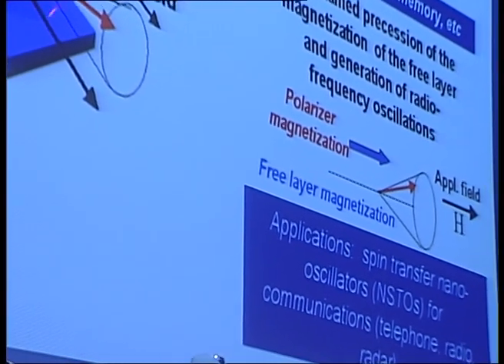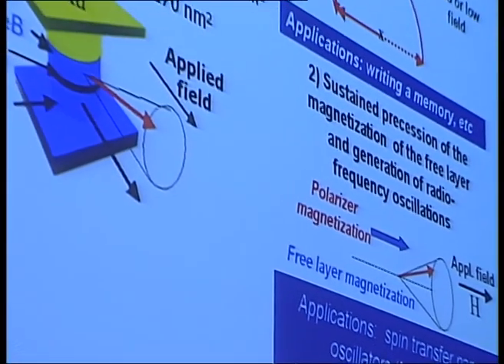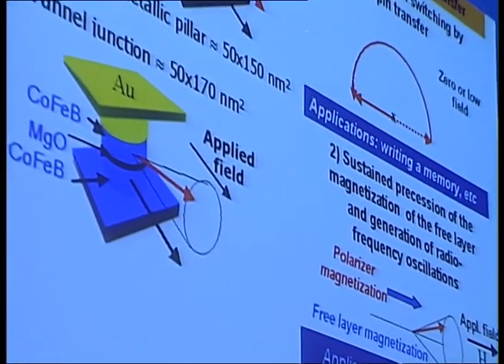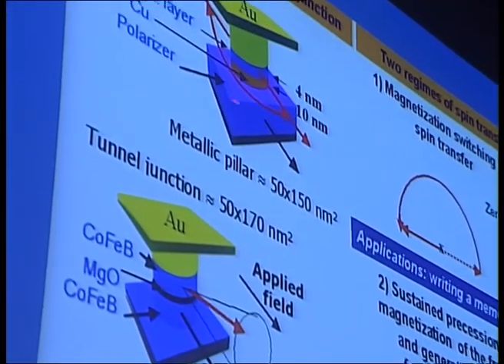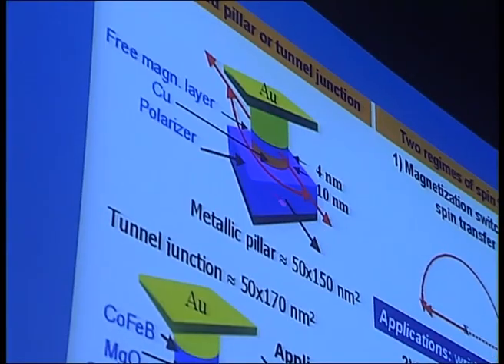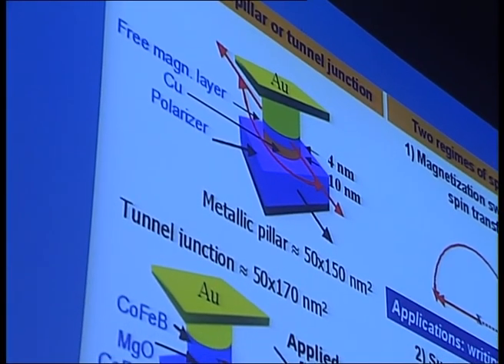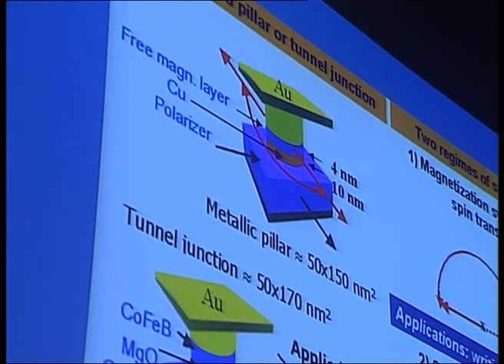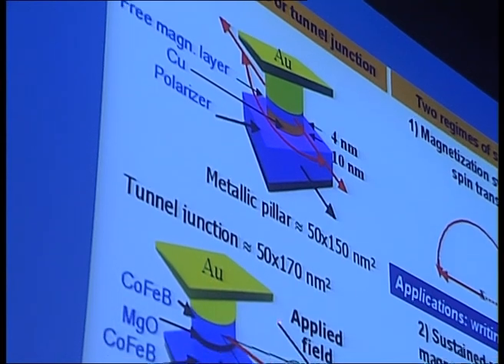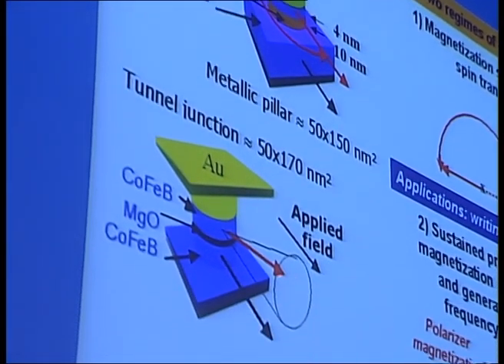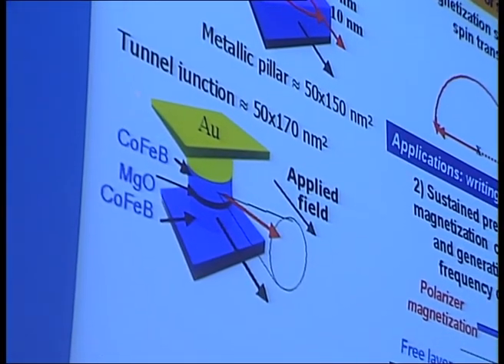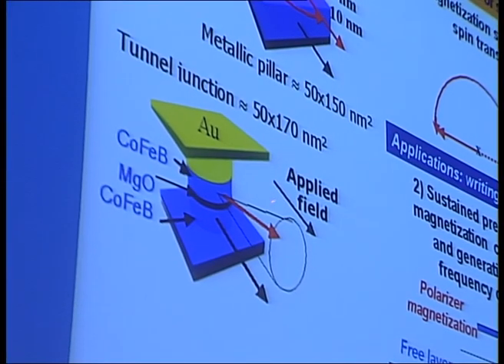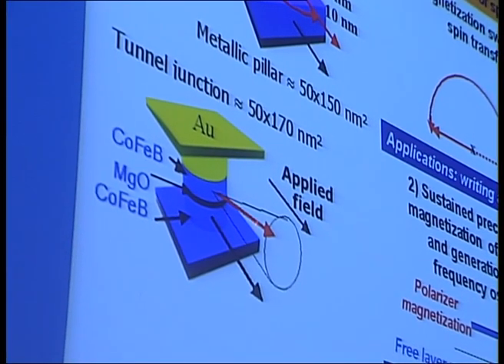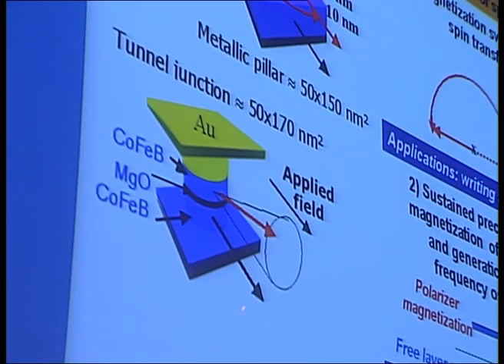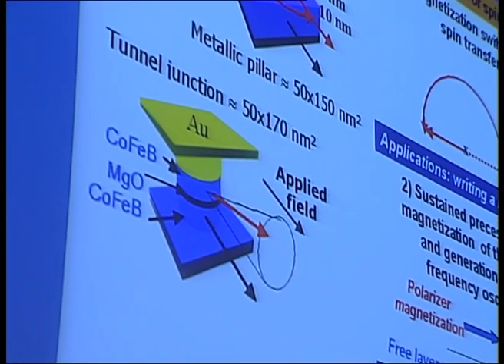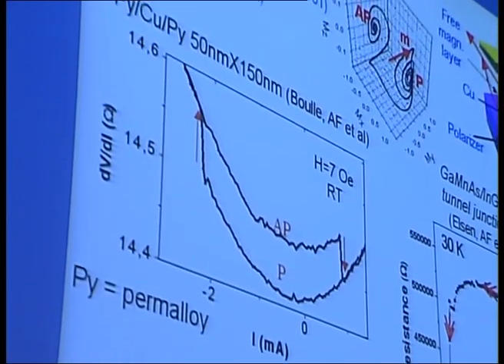So these are the two regimes. At low field, by using the spin transfer torque, you can simply reverse the magnetization, from parallel to anti-parallel. But if you apply a field, you can prevent the complete reversal of the magnetization, and the system is set in a state of steady precession with emission of microwaves. So I begin with an example of the switching regime.